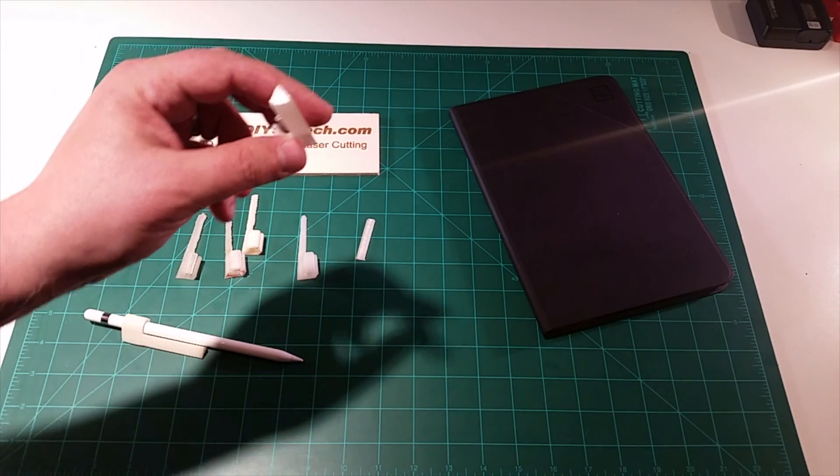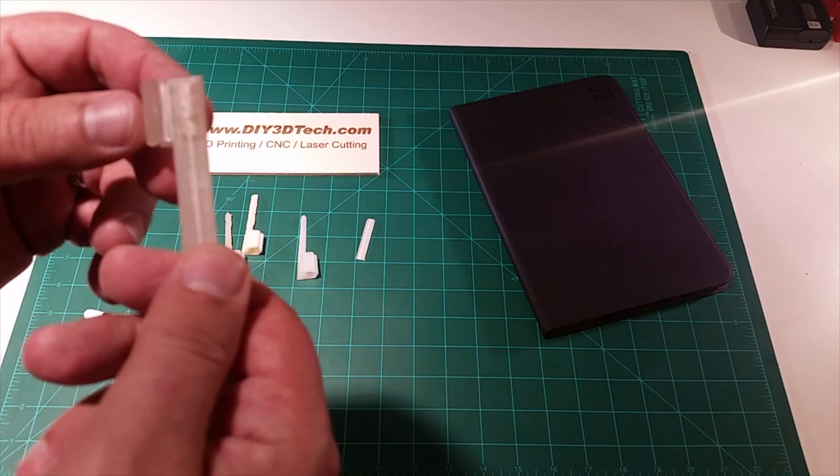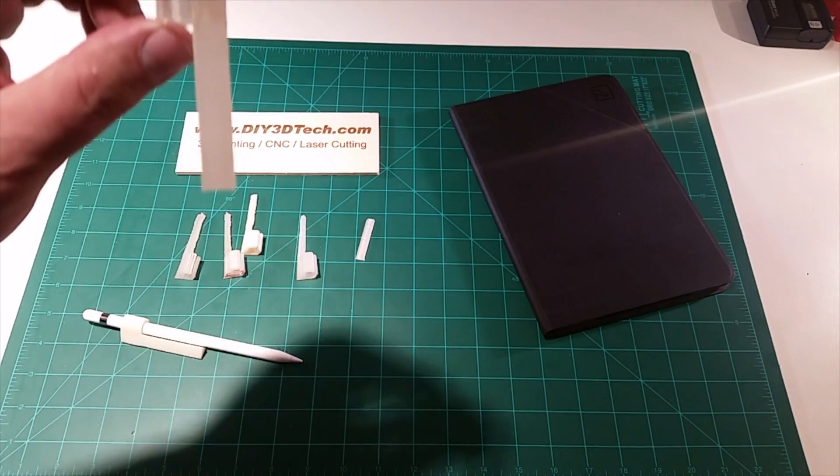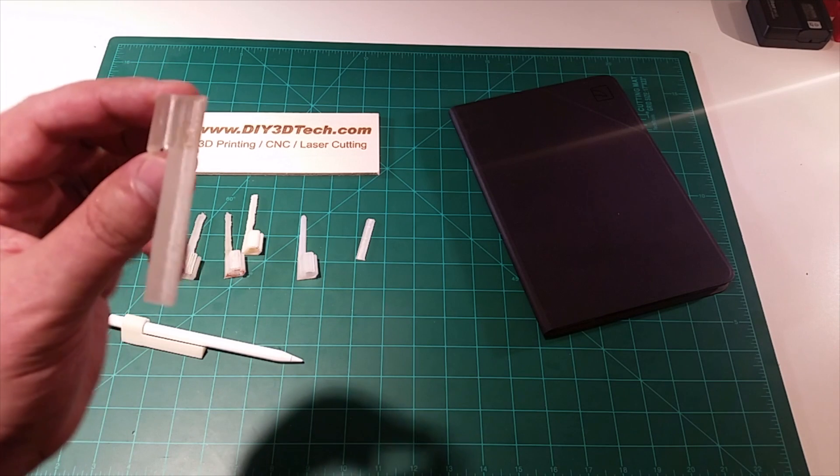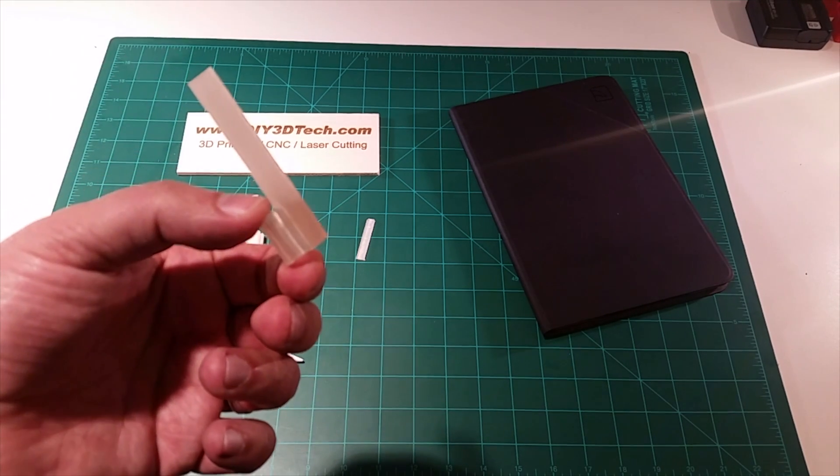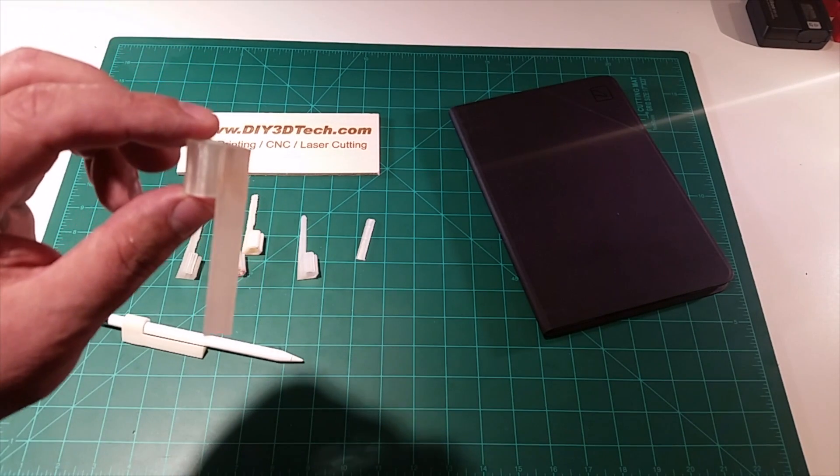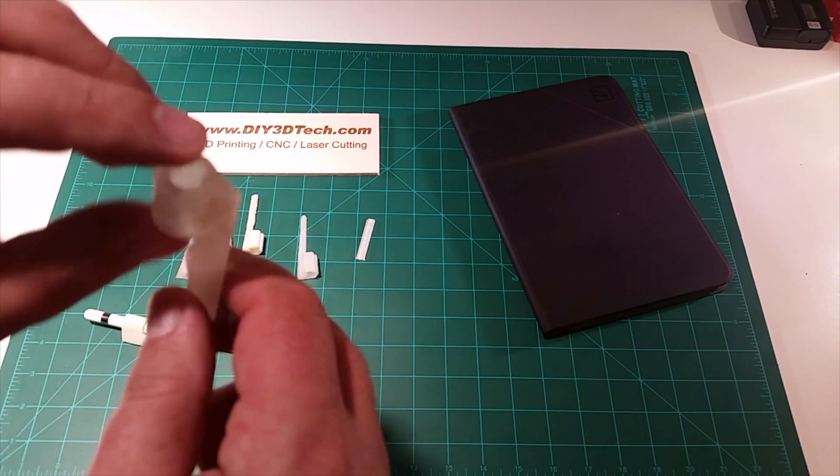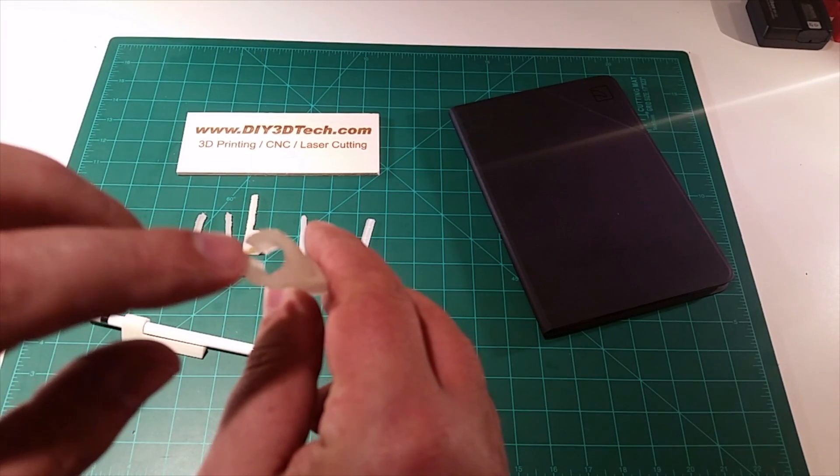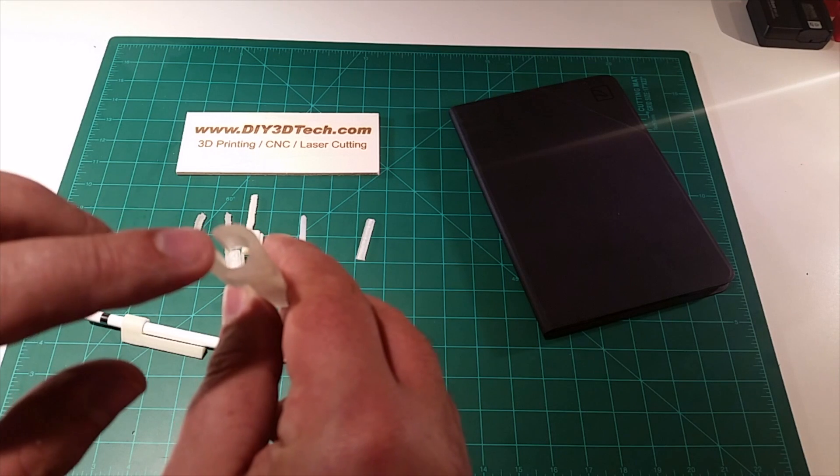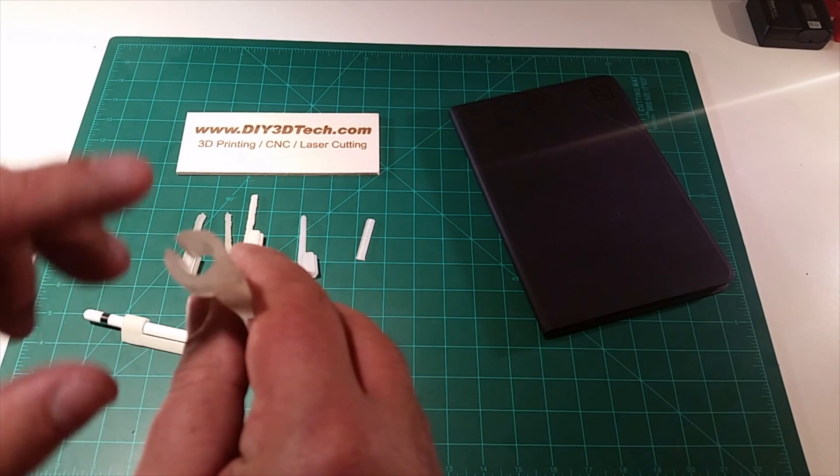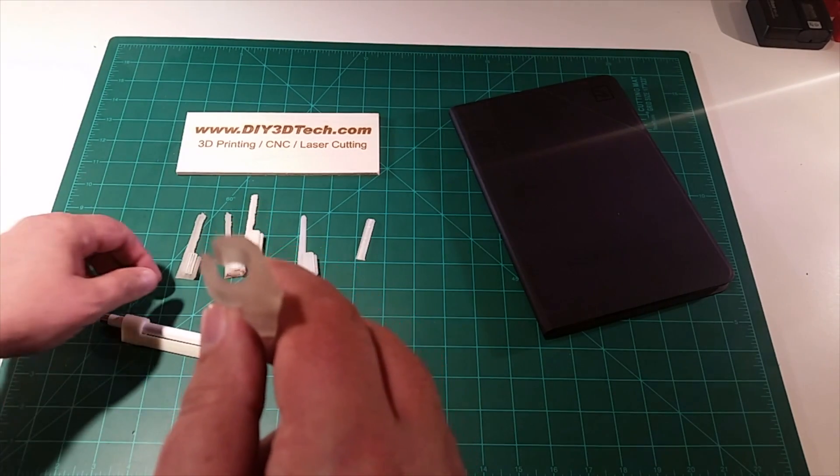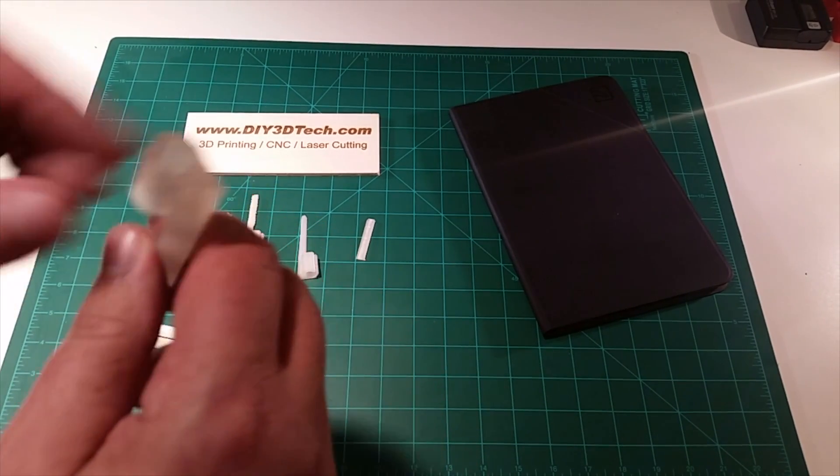This is the result of beefing up the clip and printing it on PETG. Comes out beautiful, it's translucent. The one thing I'll give you a heads up is you probably want to open up the diameter. I had to clean this one out a little bit. I would probably knock this up a hundredth of a millimeter or two because the PETG seems to be a little bit tighter than the PLA around the barrel.